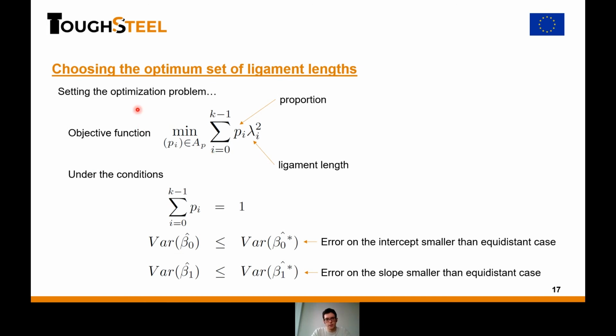So here is how I set the optimization problem. I have an objective function: I want to minimize the total amount of material. A dense sample is basically the width times the height. Since my width and my height depend on the ligament length, the objective function for the minimization of the total amount of material is simply lambda squared times a proportion, because for each ligament length I can have more or less specimens. My conditions are simply that the sum of these proportions should be equal to 1. And I impose two things. I want the error, represented by the variance on the estimator, to be lower than the equidistant case, and this for both the intercept and the slope.